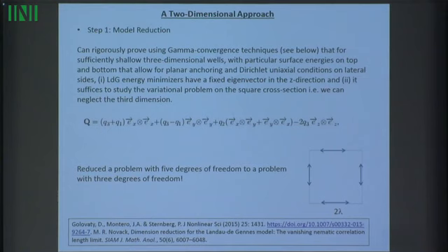It's also okay to assume invariance in the third direction, so you don't actually need to worry about derivatives in the third direction. And quite importantly, we can assume that all physically relevant states will have one fixed eigenvector in the Ez direction. So if you look at this formula, you have Ex, Ey, and Ez. These are the unit vectors in the three coordinate directions, but they prove that it is reasonable to assume that all physically relevant configurations will have one fixed eigenvector in the Ez direction.